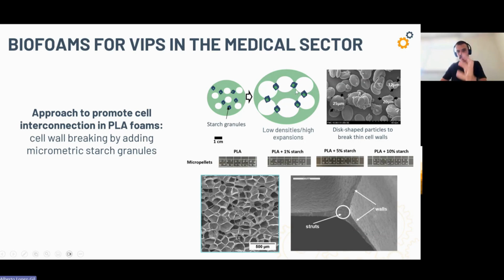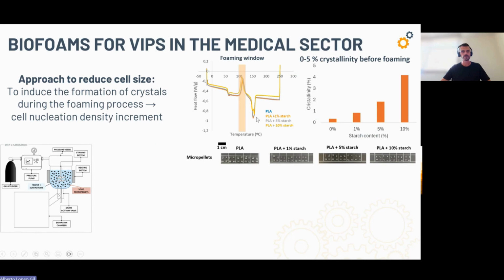But then at the end, when the expansion is very high, these particles are able to break the cell walls, which in a very low density foam are very thin. The cell walls in a foam are around 1-2 microns in thickness. And this is what we do. We produce several blends of PLA with several contents of native starch particles. As you can see here, these are the micro pellets before the foaming process.